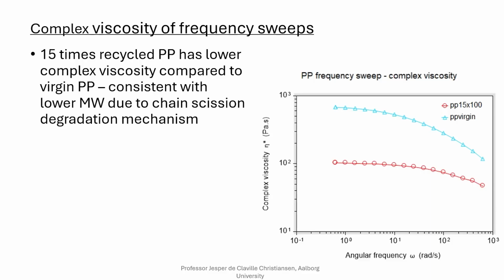So let's look at some rheological data. What we see here is the complex viscosity as a function of frequency. So the blue curve, that is the virgin material, and the red curve, that is the 15-time recycled material. And we can see due to the chain cutting that we have a lowering of the viscosity by almost a decade, which is quite significant and very important if you want to process these materials, that they get very, very thin, so that can inhibit quite many processes.